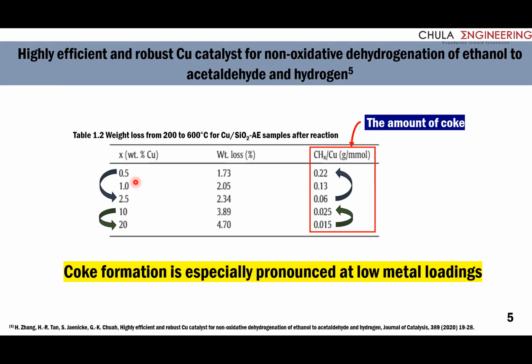The main cause of catalyst deactivation was found to be coke formation. The coke to copper ratio in the used catalyst varies inversely with loading. This slide shows coke formation is especially pronounced at low metal loading.